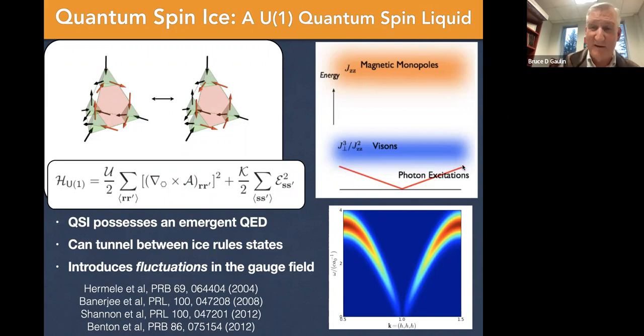And so photons, as we all know, have an energy that depends linearly on wave vector, at least at small wave vectors. So they're very much like acoustic phonons, right? Their dispersion relation would look like acoustic phonons, and that's what's represented down in this lower right-hand corner, except that the spectral weight for these emergent photons, as measured with neutron scattering, at least in this model, is such that the spectral weight actually goes away as you go to the magnetic zone center, right? It's the exact opposite of acoustic phonons, where the acoustic phonons get stronger and stronger as you go down to the zone center.